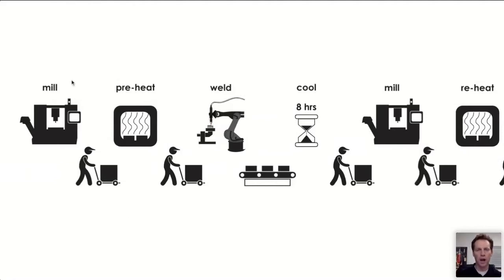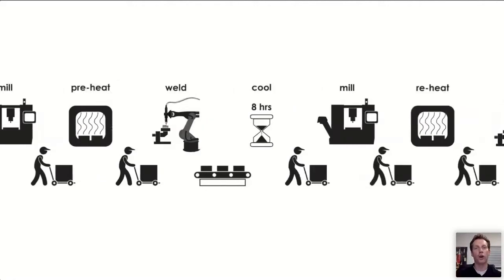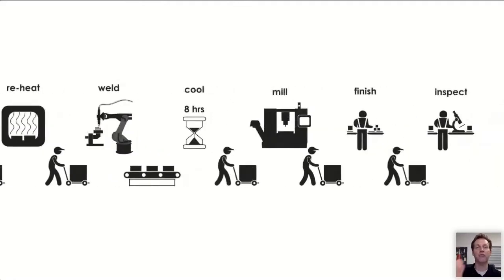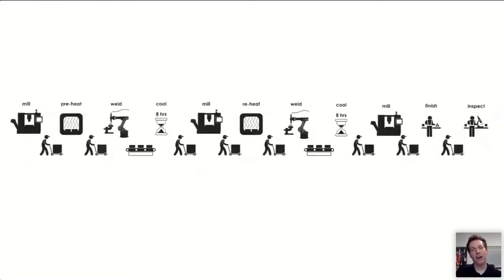Now, if it were only this complicated, it would certainly justify trying to hybridize and co-locate some steps. But what actually happens is the very characteristic that they're after in performance of the mold, which is the ability to draw heat out, also causes them to have to repeat this cycle of preheat and deposition because the mold won't stay hot enough for long enough to do all the welding that's needed. So a portion of the welding happens, a portion of that weld gets milled away, and then they reheat it, do the whole thing all over again. And so you can see these 8 or 9 or 10 steps are a lot of steps.